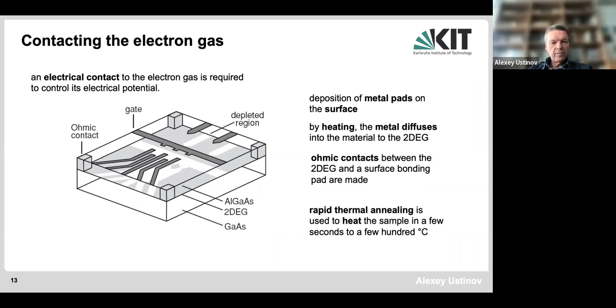And then you also need to make a contact to this two-dimensional electron gas and also to the gates. So top structures are called gates, and the two-dimensional gas is at some distance below the surface, as I already explained. So in this case, you have to deposit some metallic pads here, and then use some moderate heating to make the metal diffuse into the material of the two-dimensional electron gas and form an ohmic contact to the two-dimensional electron gas. And then basically you can connect your wires to the two-dimensional gas, and you connect your wires to the top gates. And that's basically standard procedure, for example, of making high mobility transistors or making structures for low temperature transport studies of low dimensional systems.